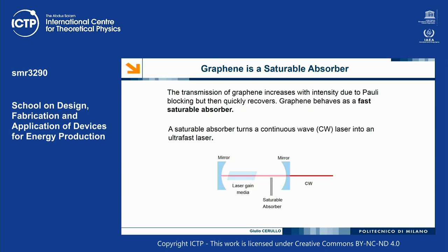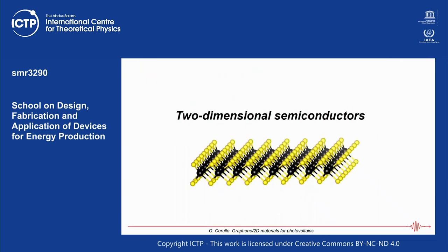This ultrafast switching has applications: graphene can be used as a saturable absorber inside a laser. It acts like a switch that opens at high intensity but then closes immediately, forcing the laser to emit light as a train of pulses. You place graphene inside the laser and automatically it enters a mode-locked regime, finding it more convenient to emit a train of pulses rather than a continuous wave, since these high-peak-power pulses have higher transmission through the graphene.